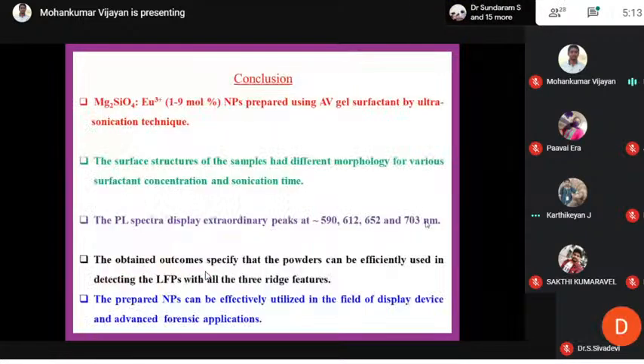So the conclusions are: Mg2SiO4:Eu nanophosphor was prepared using aloe vera gel as surfactant by the sonication technique. The surface structure of the sample has a different morphology for various surfactant concentrations and sonication times. The PL spectra display peaks at 590 nanometer, 612 nanometer, 652 nanometer, and 703 nanometer. The obtained outcomes specify the powder can be efficiently used in detecting latent fingerprints with all three ridge features. The prepared nanoparticles can be efficiently utilized in the fields of display devices and advanced forensic applications, sir.